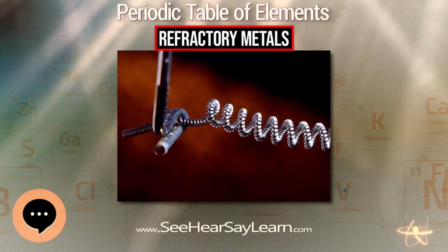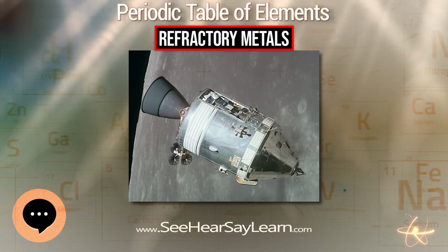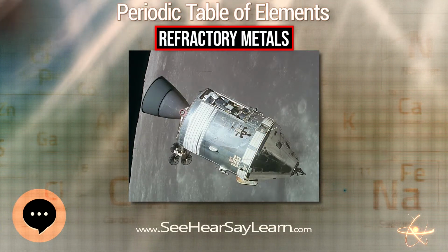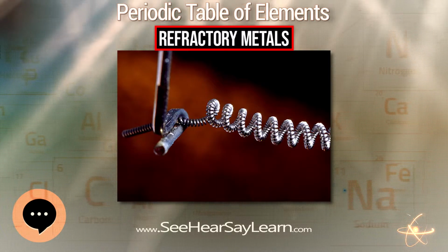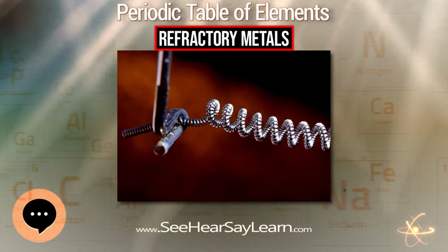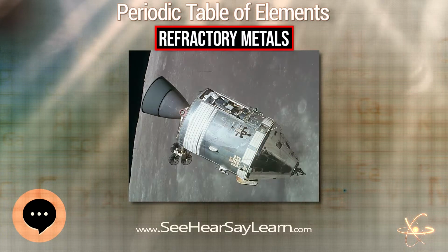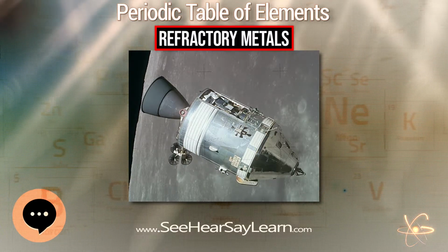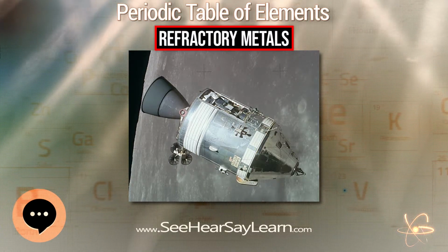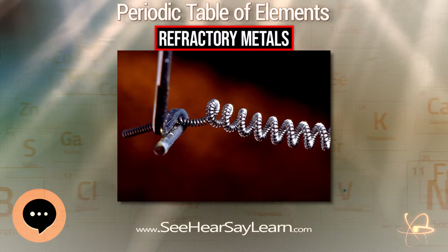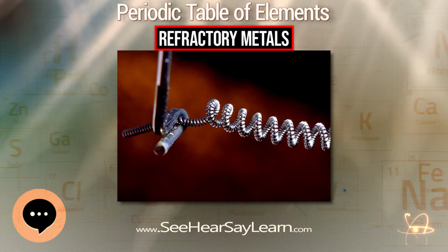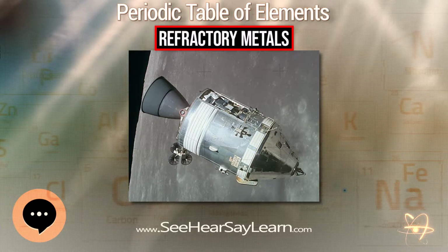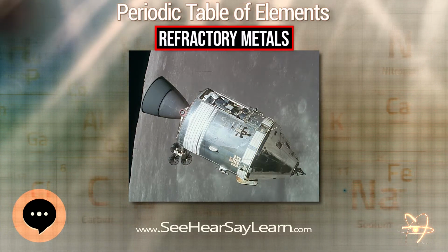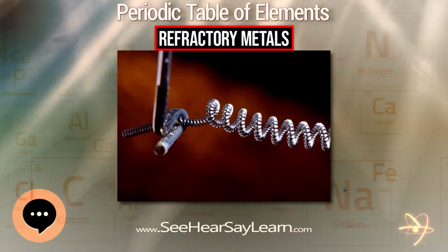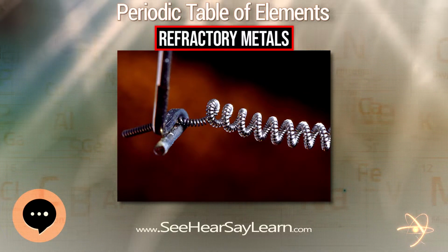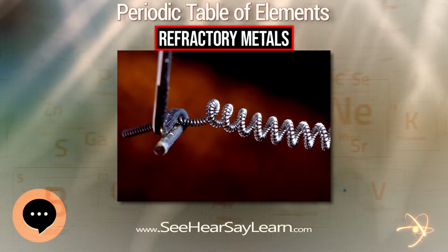The refractory metals show a wide variety of chemical properties because they are members of 3 distinct groups in the periodic table. They are easily oxidized, but this reaction is slowed down in the bulk metal by the formation of stable oxide layers on the surface. Especially the oxide of rhenium is more volatile than the metal, and therefore at high temperature the stabilization against the attack of oxygen is lost, because the oxide layer evaporates. They all are relatively stable against acids.